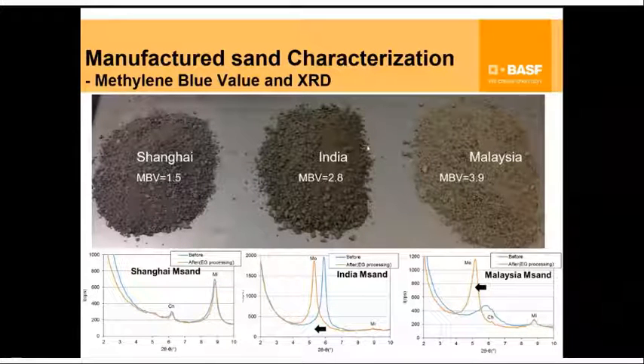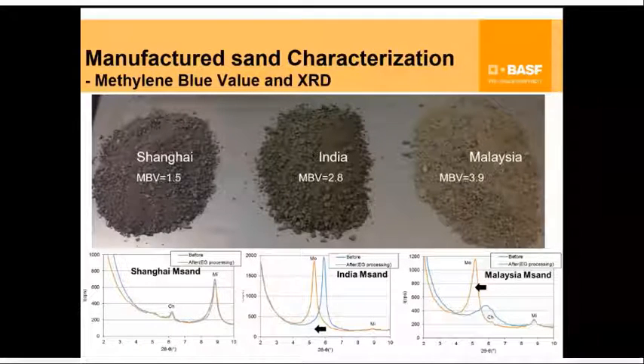To understand whether you have expanding clays, you need to do an experiment called X-ray diffraction, where you basically put a material to force the clay to separate out, and the blue and the yellow line tells you whether the clay platelets have separated. So in the Shanghai sand, for example, there isn't a lot of expandable clay, because even when you add a small amount of chemical, it doesn't separate out. That means these are not platelet type materials. Whereas in the India sand, and more so in the Malaysian sand, you can see these peaks separating out, which means that the clay is actually expanding. And the degree of expansion is basically the differential between those peaks.